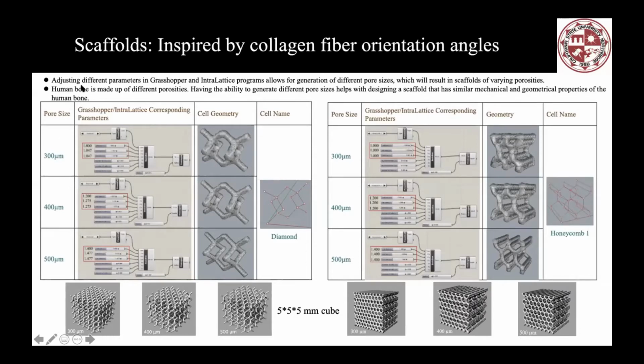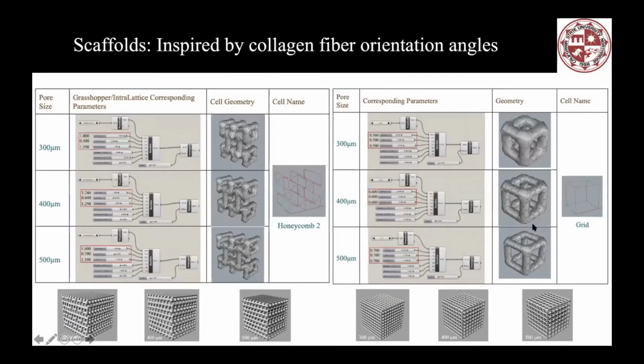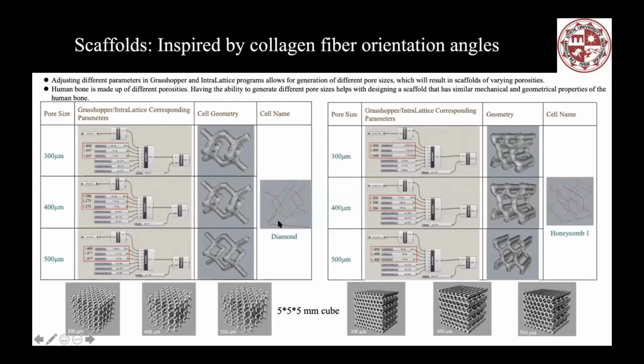And we adjust the different parameters, for diamond, the honeycomb 1, honeycomb 2, and the last one is the grid. So these four different cell structures, and then these are the three different pore sizes. And then we generate a 5 by 5 by 5 millimeter cube. So this is our final scaffold size.